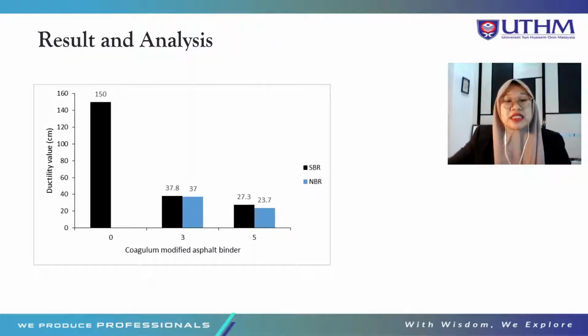This figure shows the ductility values for modified asphalt binder. Asphalt binder with 0% concentration elongated more than 150 cm. The ductility of coagulum modified asphalt binder decreased with increasing SBR and NBR concentrations. This indicates that with the increasing percentage of SBR and NBR in asphalt binder, the stiffness of the modified asphalt has increased. From the figure, the base binder with 3% concentration of SBR and NBR shows a decrease from more than 150 cm to 37.8 cm and 37 cm.